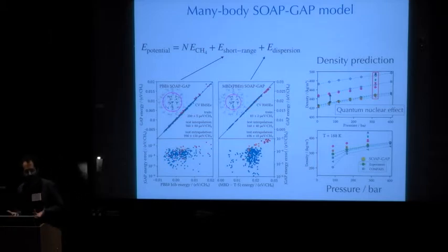And that, quite unexpectedly, for this system, turned out to be the missing last 5%. So if we really go all out, do the best quantum chemistry we can, regress it with this good kernel and kernel ridge regression, and then it's fast enough to solve the nuclear Schrödinger equation on top, we actually get the equation of state of methane. So these yellow points are right on top of experiment, and for the right reason, because we are actually getting the potential energy surface right.